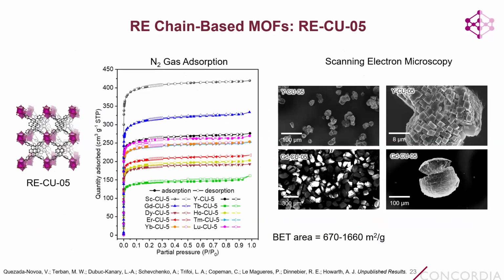So this MOF is also permanently porous. So we have these nice nitrogen gas adsorption isotherms, BET areas up to 1660 meters squared per gram. And we can see in the scanning electron microscopy images these kind of spherical structures that we obtain, which if we look a little bit closer, seem to be made up of little cubic and rectangular crystallites. So these were unfortunately not suitable for single crystal X-ray diffraction or for electron diffraction, which is why we turned to the total scattering data.